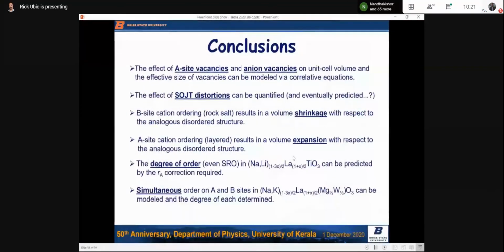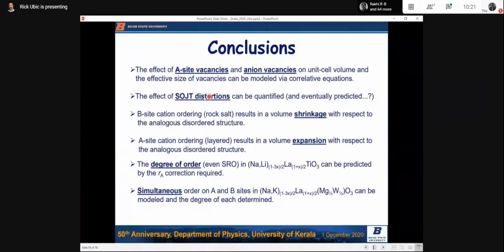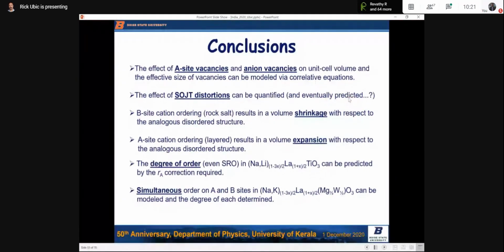So my conclusions: the effect of A-site vacancies and anion vacancies on unit cell volume, and the effective size of those vacancies, can be modeled via these correlative equations. The effect of the Jahn-Teller distortions, second order Jahn-Teller distortions, can be quantified. We can't predict them yet, but I think with a bit more work on more compositions, again, for correlative models, they're all empirical. You need data to create them. So with more data, I think we can probably do this.